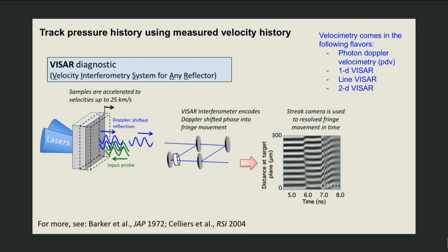So a little bit about the diagnostics. One of the ways that we track pressure is by using velocimetry, so looking at the speed of either the shock wave or the particle wave as a function of time, and then extrapolating that back into what the material properties are at the sample conditions themselves. And so we can do this a few different ways using either point or one-dimensional or two-dimensional velocimetry. PDV is one dimension, and we can do line VISARs.